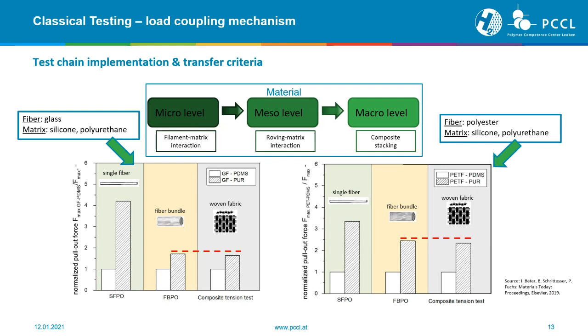a woven fabric. And as you see here, for different materials, the left side for silicone polyurethane with glass fiber, and on the right side for the matrix material silicone polyurethane with polyester fiber, we see the normalized pull-out force. We received, for the fiber bundle test, for the woven fabric test, and for the single fiber test, at least the same tendency, the same trend, which means that we can characterize much more easily with the fiber bundle, and a little bit more application oriented compared to the single fiber test.